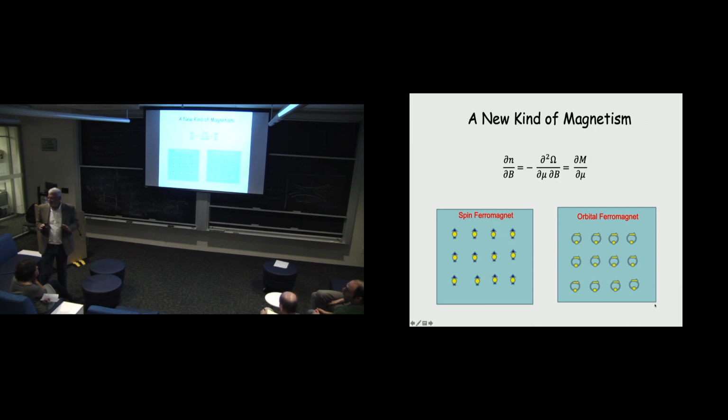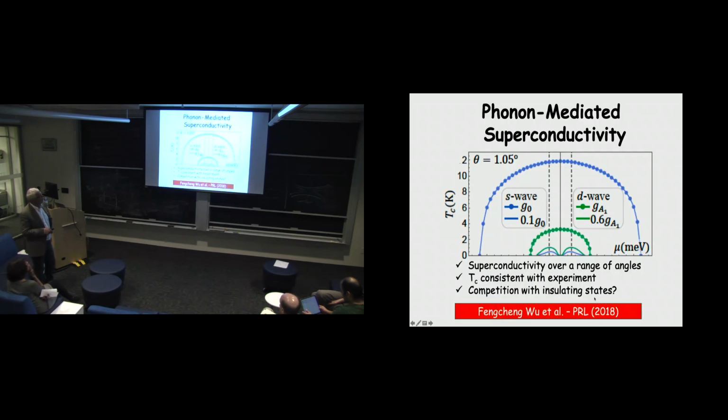These graphene sheets are known for having practically no spin-orbit coupling on the micro electron volt scale. And so orbital and spin space can break time reversal separately. In this case, it's orbital space that breaks time reversal symmetry and produces anomalous Hall effect, and we think eventually, as the samples improve, quantum anomalous Hall effect.